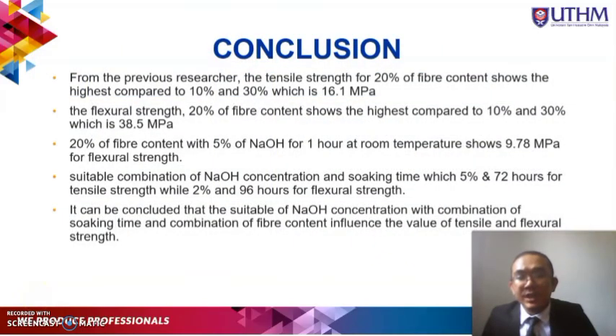Alright, for the conclusion, from the previous researchers, the tensile strength for 20% coir fiber content shows the highest compared to 10% and 30%, which is 16.1 MPa. The flexural strength for 20% fiber content shows the highest compared to 10% and 30%, which is 38.5 MPa.